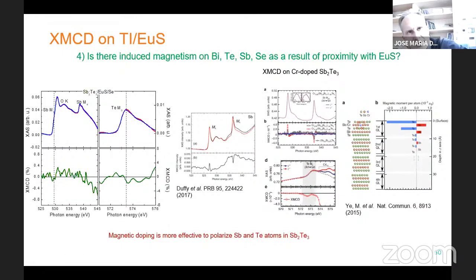So I was wondering if you have characterized the bismuth selenide films with magnetotransport at low temperature, because if you study the weak anti-localization effect in films, you have a lot of information there. If you have conduction by the surface states, the top surface state, the bottom surface state, the bulk states. Yeah, definitely. That is a very relevant question, because